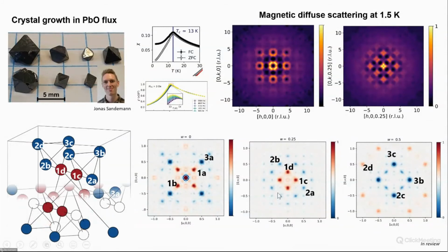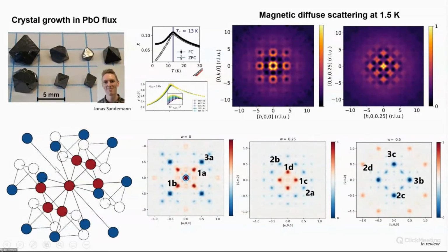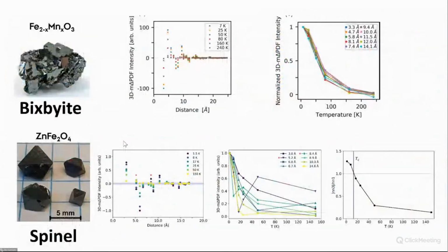What you see here is that in this pyrochlore lattice, you get a ferromagnetic core, and then primarily in the third nearest neighbor, you have antiferromagnetic correlations. One thing that contrasts Bixbyite and spinel is that if I integrate my 3D delta PDF, then in Bixbyite all the peaks have approximately the same temperature dependence, whereas in spinel some of the peaks go from negative, so antiferromagnetic, to ferromagnetic, and it's really, really funky.